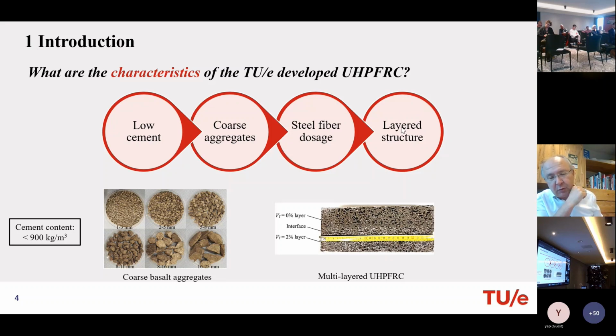So we work with layered structures where fibers are applied in some parts and some parts not. The dosage we optimized. We looked critically at how much steel fiber dosage is needed. Then we introduce coarse aggregates, because if you introduce more and coarser aggregates, fewer fines are needed. And if you look at the fines, we looked at how much of the fines we could substitute by fillers. So all these measures help in reducing steel and cement. Here you see already a layered structure where we have a layer with 0 fibers, and we have a layer with 2% fibers, where the tensile forces are taking place.